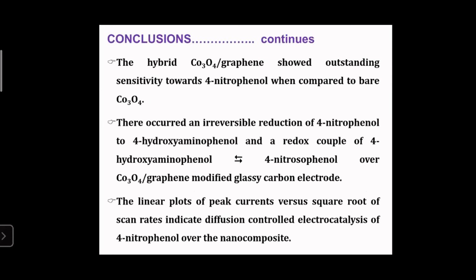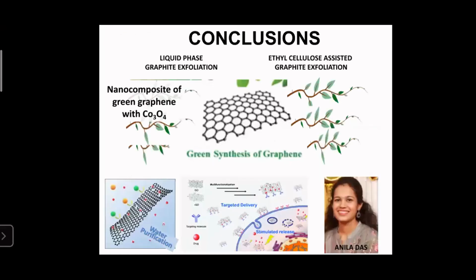In the electrocatalysis reaction, there occurred an irreversible reduction of 4-nitrophenol to 4-hydroxyaminophenol and a redox couple of 4-hydroxyaminophenol to 4-nitrosophenol over the Co3O4 graphene modified glassy carbon electrode. The linear plots of peak current versus square root of scan rates indicate diffusion controlled electrocatalysis of 4-nitrophenol over the nanocomposite. So in conclusion, we can successfully report a liquid phase exfoliation of graphite using ethyl cellulose as an exfoliating agent, and we could produce a nanocomposite of Co3O4 with this graphene, and it can be applied for other applications such as pollutant degradation, drug delivery, etc. This work is mainly done by my student Anila Das during her MSc project work.